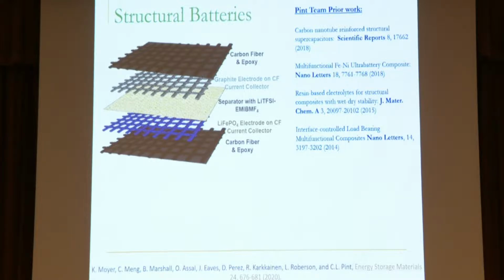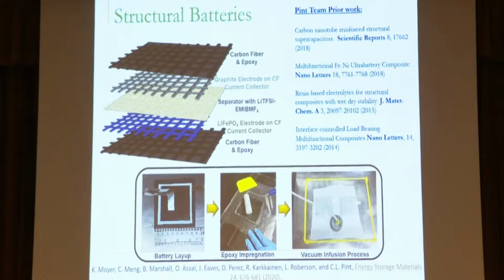We simply used carbon fiber and epoxy. We used standard processing techniques, but we integrated inside of the system lithium iron phosphate, which is a cathode material, graphite, which is an anode material, and we put in a little bit of ionic liquid, which is a material that allows ions to move back and forth in between this composite. So we were able to develop these carbon fiber composites using standard processing techniques, which are also batteries.